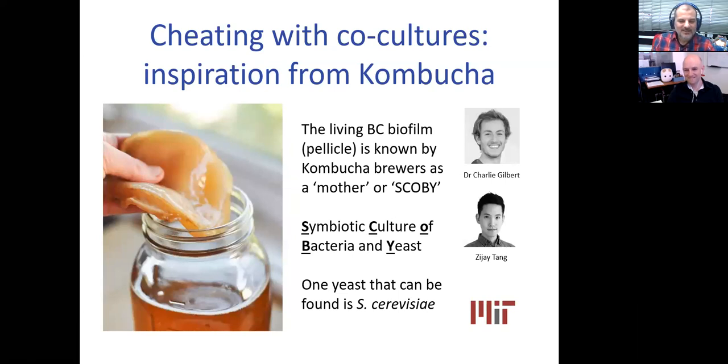Yeah. So another question is, Amparo Lopez congratulates for a fantastic seminar and asks if there is any way to continuously produce the bacterial cellulose. Yeah, so continuous production. We do what we would call batch production. We take a flask, leave it sitting there, and the material will start to appear after 3 days. If you want a big thick layer, you might wait 2 weeks and then take that off. If you were to wait a month, it doesn't really get that much better because you've started to exhaust everything.